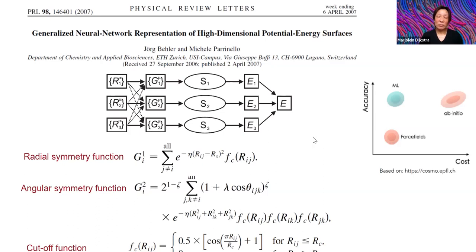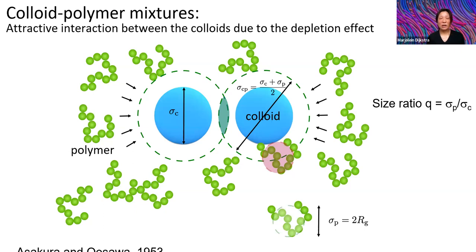To fit the potential energy functions, they introduced so-called symmetry functions that really describe the local environment of all the atoms. Here we actually did the same for a so-called colloid-polymer mixture. Often, if you do self-assembly experiments with colloidal particles and you want to tune the interactions of the colloidal particles, you can either add salt to the suspension to change the interaction, or you can also add non-adsorbing polymer to induce basically attractive interactions between the colloids.